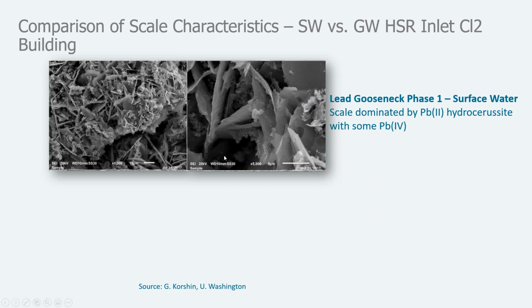And when we look closer in at the scales, this is at 1,000 times magnification and 5,000 times magnification. We do see these beautiful, perfect hydrocerussite crystals that form, minerals that form during phase 1, which is expected with the surface water. And on top of it is the lead 4 being formed. And I thought this was just so interesting because the chlorine is oxidizing the hydrocerussite scale to form lead 4. So that's exactly what's happening with the chlorine on top of these scales, forming a lead 4 coating, which reduces the solubility of the lead.